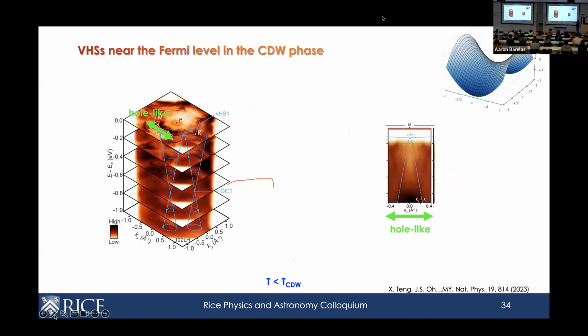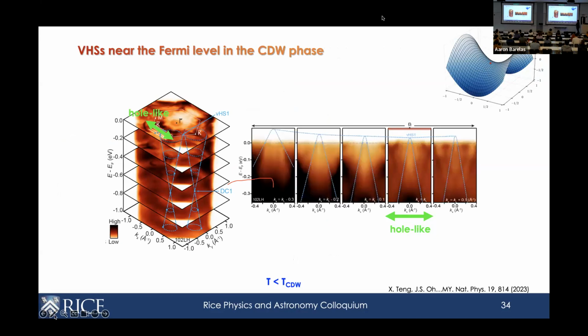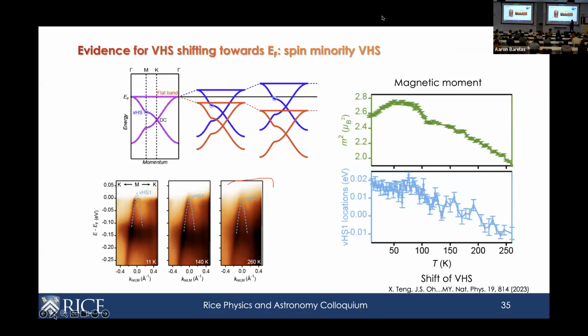So if you look along the zone boundary, you can see that this is a hole-like band. And we can track where the band top is. And if you walk in parallel to the left and to the right, you can track where that band top is. And you can see that while it's pointing down in this direction, in the perpendicular direction, it actually points up. So this demonstrates that this band dispersion actually does follow the shape of the saddle point. So therefore, this is indeed a saddle point. So that matches what's expected here.